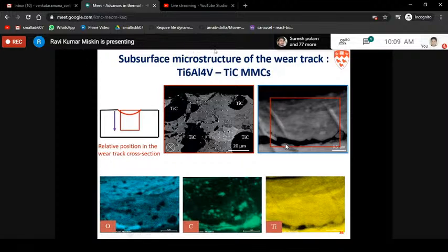In that tribofilm, if you start mapping your elements below, you could see oxygen and also those small particles. That was the oxygen map, and the second one is the small particles. The small particles were basically carbide particles. Inside the tribo layers, those small particles are fragmented particles. You can imagine this like a cake with cherries inside it. The cake is soft, so the matrix is soft, and the cherries are considerably harder. That cherry is basically your carbide particle. That's the composite effect you're getting. You have something which is taking more stress and also improving its hardness. That's why you don't lose the wear, you get the wear resistance. That layer is formed on top of the composite wear track, and it actually prevents your base material from wearing out during actual application. Go to the next slide.